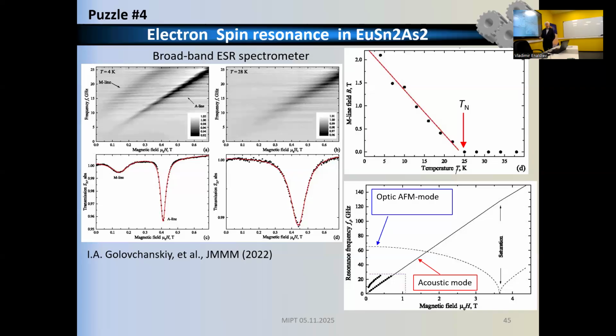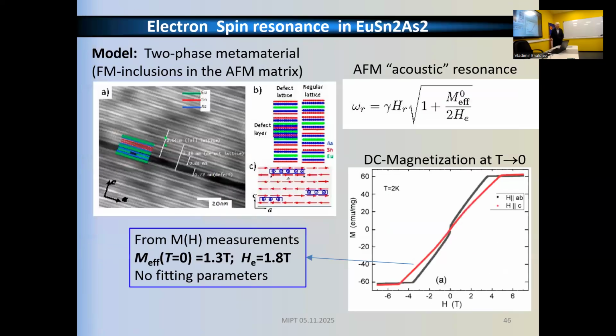But again, we already suspect that this is not impurities, but defects. And the only thing which Igor concluded is that it doesn't have anything in common with the optic antiferromagnetic resonance. What's important also is that the amplitude of this line vanishes exactly at the temperature of magnetic ordering. So again, it originates from the same antiferromagnetic ordering.